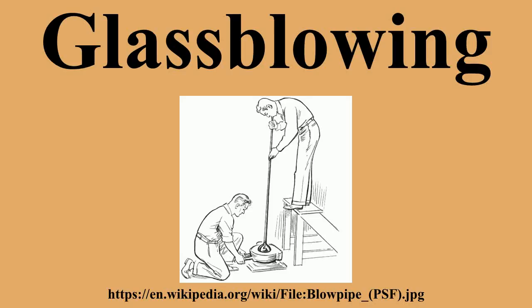During blowing, thinner layers of glass cool faster than thicker ones and become more viscous than the thicker layers. This effect allows production of blown glass with uniform thickness, instead of causing blow-through of the thinned layers. A full range of glass blowing techniques was developed within decades of its invention. The two major methods of glass blowing are free blowing and mold blowing.